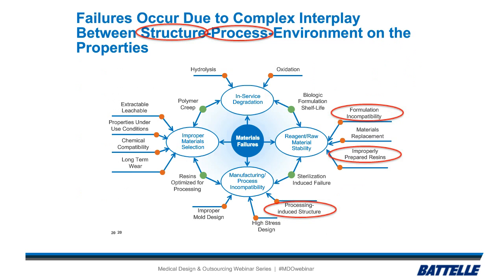This one we believe was structure and process. Structure being the processing-induced structure, so that mixing at the higher temperature was the process-induced structure. And then there was also formulation incompatibility, which is tied up in the processing, and improperly prepared resin. So, again, this is a complicated mix of at least two of these three factors going wrong at the same time and causing some of the material to fail.